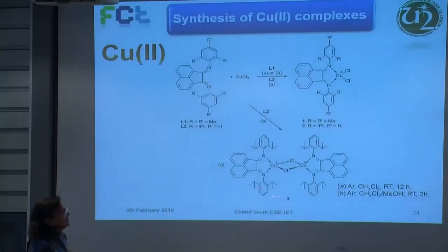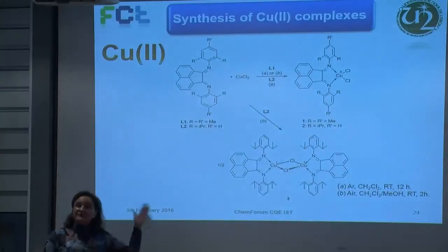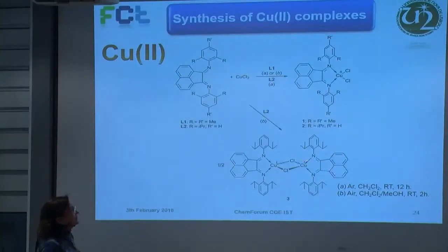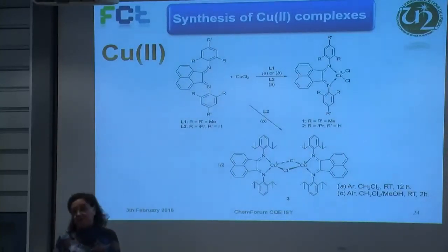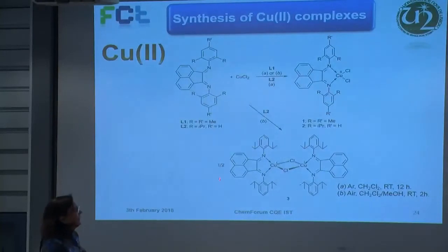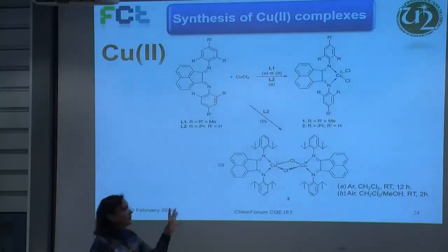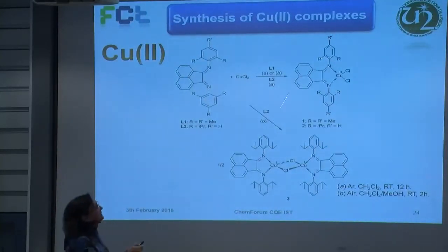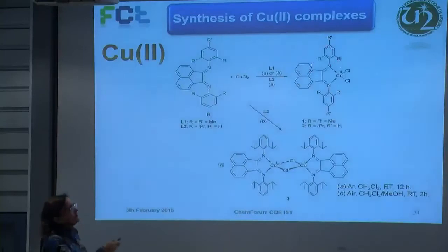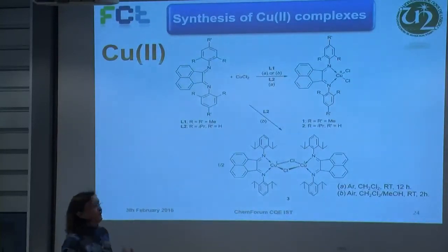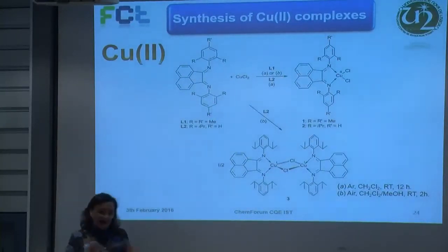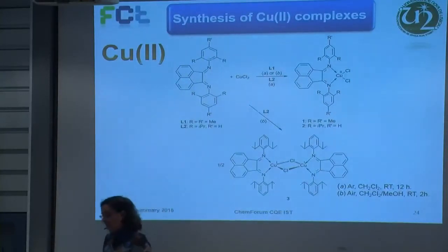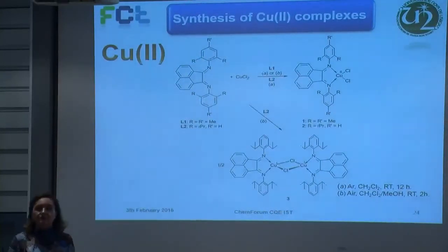We isolated this dimer compound, which we had seen before, we had synthesized by another route, but in this case, we got a reduction in air. So we were very surprised, and then finally, we came to the conclusion. We also compared the two ligands, why one doesn't make the reduction and the other one does. So we asked people to do the electrochemistry and some theoretical calculations and finally reached the conclusion.